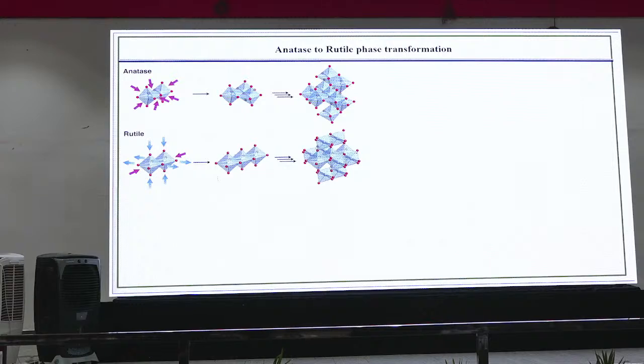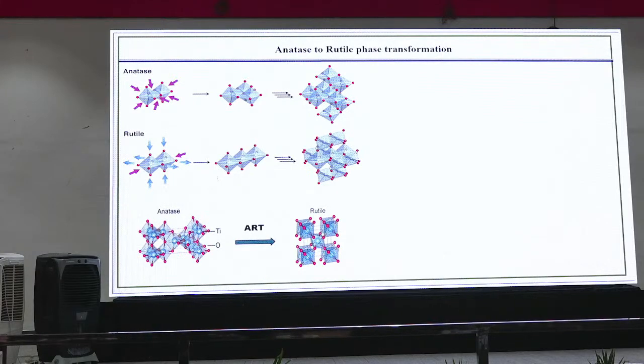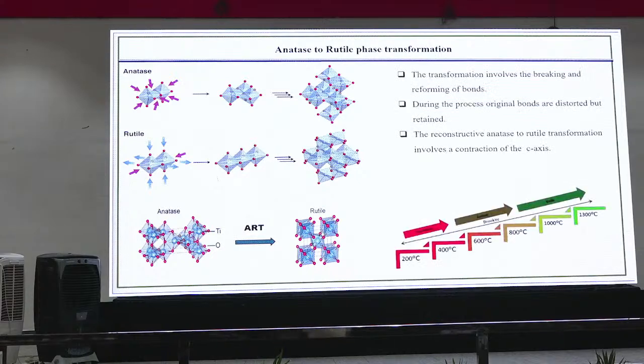So anatase is the one which has an octahedral geometry. You can see the anatase and rutile both have an octahedral geometry, but the way they are arranged makes the phase. So when they arrange like this, we get anatase and rutile. In the anatase, it is arranged in a cross way and a side way, but in rutile, it is arranged only in the cross way. So when I did the ball milling, what exactly happened? During the process, the anatase has been converted into rutile. This is what we usually used to do.